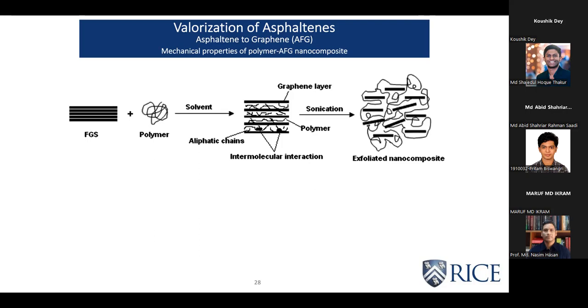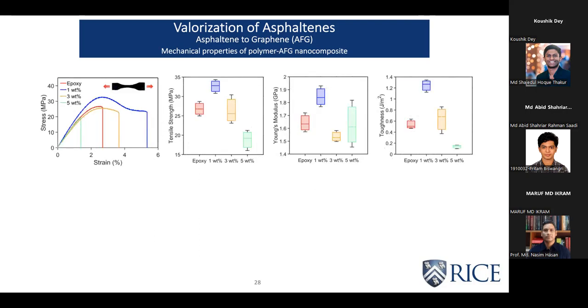And after the composites were formed, we tested their mechanical properties. And as you can see, at 1 weight%, the mechanical properties improved compared to the neat epoxy. However, at higher percentages, the properties degraded. This is possibly due to the aggregation of these particles, because if you keep on increasing the nano reinforcements, at some point they start aggregating again, which start acting as stress concentration zones and crack initiation sites.